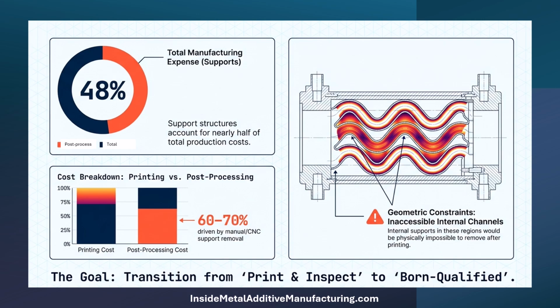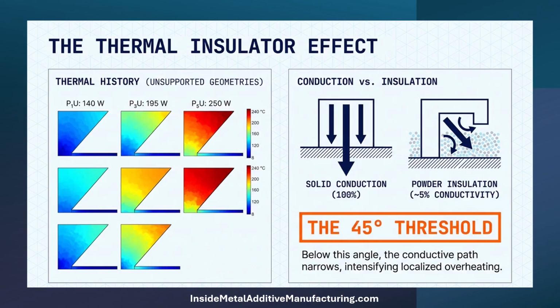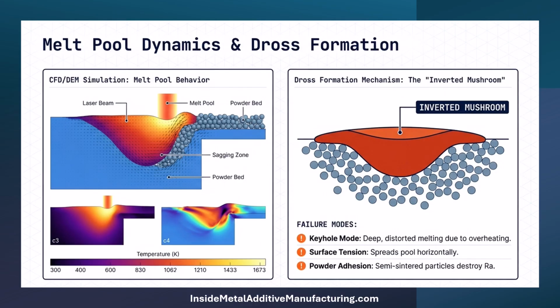build ends. To solve the overhang problem, we have to understand the physics of the powder bed. Solid metal is an excellent conductor, but loose powder acts as a thermal insulator, possessing only about 5% of the conductivity of the solid part. As we approach the 45-degree threshold, the conductive heat path narrows significantly, trapping energy and intensifying localized overheating. This trapped heat causes the melt pool to transform into what we call the inverted mushroom.